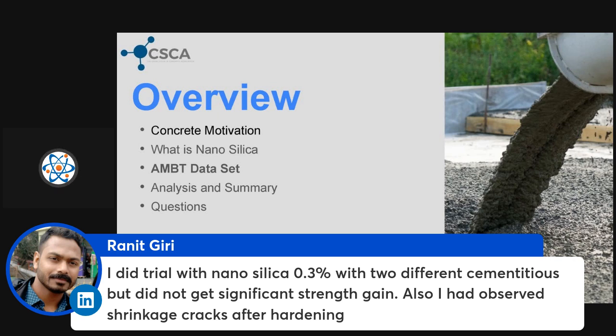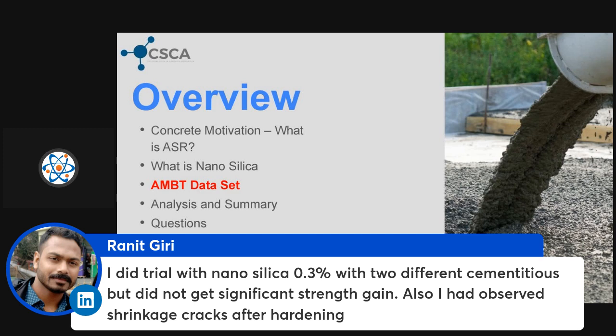Ranit, I did trials with nanosilica at 0.3% with 2 different cementitious materials, but did not get significant strength gain. I've also observed shrinkage cracks after hardening. It sounds like, Ranit, you need to use a different type of nanosilica. If you saw any type of strength gain, especially early strength gain, you might have been using too small of a nanoparticle size, like 3 to 5 nanometer, especially if you observed shrinkage cracks after hardening. We can get into what better types of nanosilica there are, but basically you want to go for a larger particle size, ultimately to control that hydration. But I would need a lot more information, Ranit.